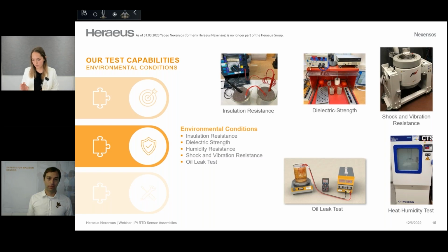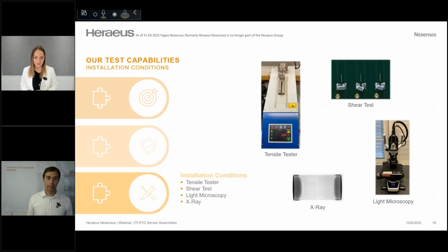And the last very crucial test setup here is the heat humidity test. So we don't only expose the sensor to a temperature, but also to humidity. This test could also be called an 85-85 test. So we expose, for example, the sensor for 500 hours at 85 degrees Celsius and 85% relative humidity. All right, next slide.